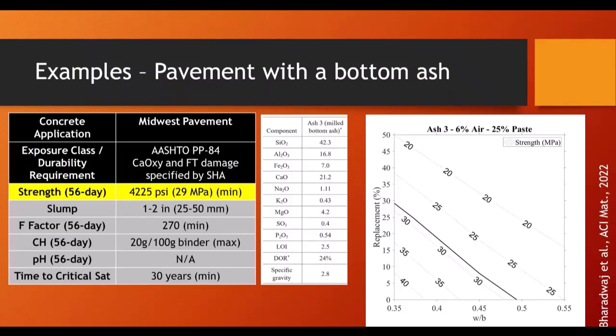Now, if we started to look at this, we could actually start to design our pavements and our bridge decks differently. Instead of just designing them using the standard 12-step process, all right, that 211 or other mixture proportioning procedures give us, we could actually say, tell us what you really want that structure to do in the field, and we can optimize the mixture for that particular scenario. So here's a pavement where we want a certain strength, we want a certain formation factor, which is like the resistivity that Tom mentioned, but it accounts for the pore solution.